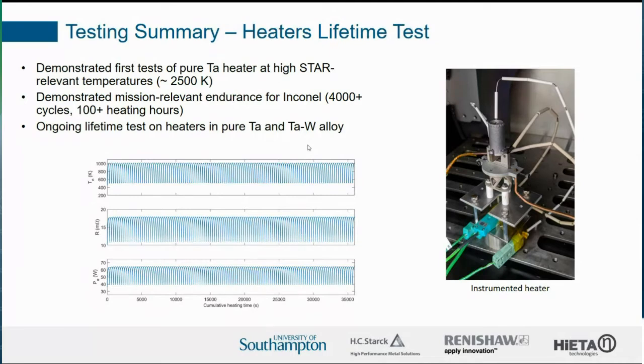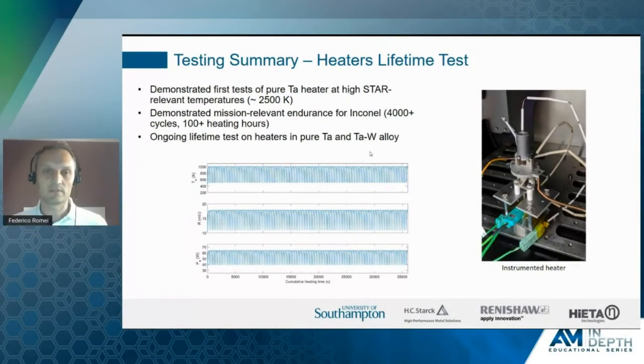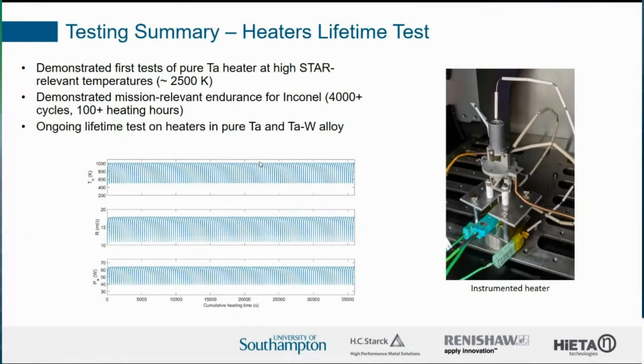So in particular, we have been given requirements from SSTL for lifetime, roughly speaking, corresponding to 1 maneuver per day for 7 years of operation. And we already passed the requirements for Inconel, and we have very promising results for tantalum and tungsten as well. So typically, you see in the chart in the middle, we're measuring temperatures and resistance, so that we are able to trace any change in particular resistance that would highlight any degradation of the material.